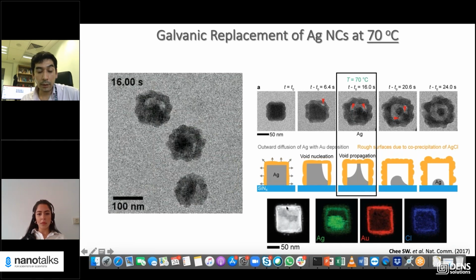I guess the concentration of silver is slightly higher at this interface when it initially starts depositing. So this one is inside of this one, and it matches with silver, right? The outer interface of the silver and the gold has a silver chloride distinctly here. So here you have a silver chloride, and you have a very diffuse silver and gold, very rich in gold. But you do have a chloride at the interface, because even at 90 or 70 degrees in this particular case, it is still present and does not dissolve fully.